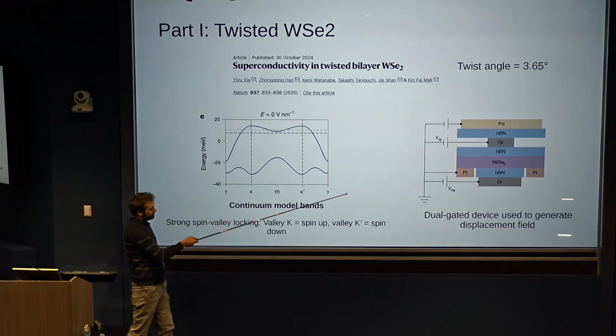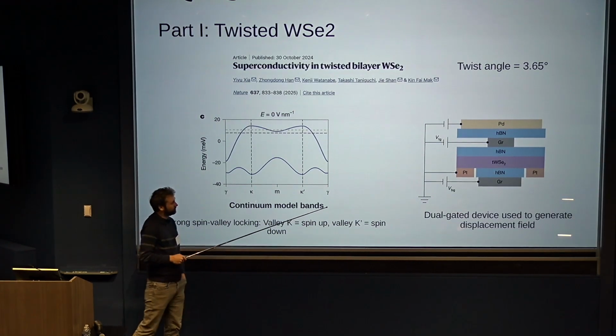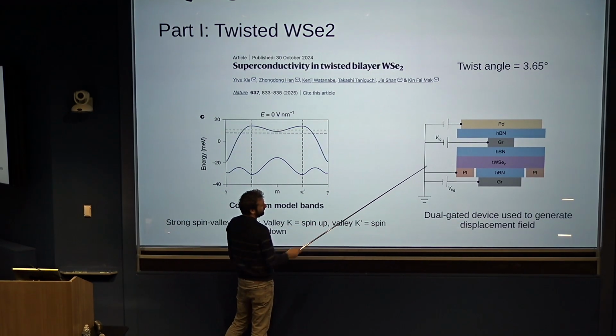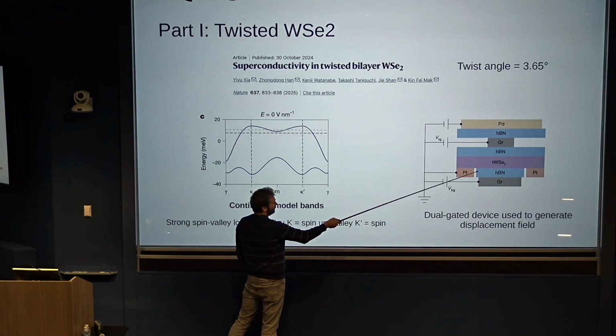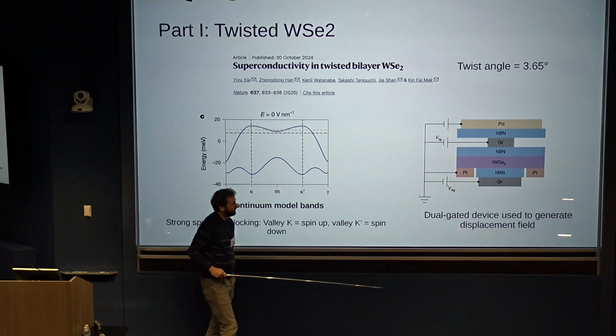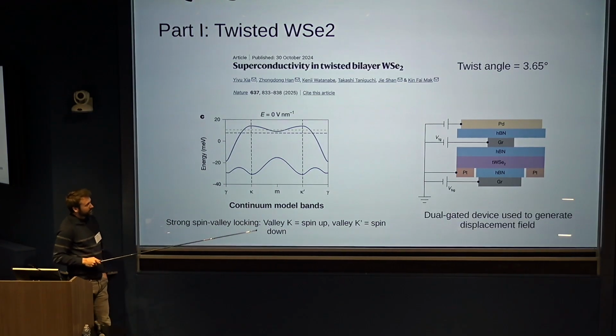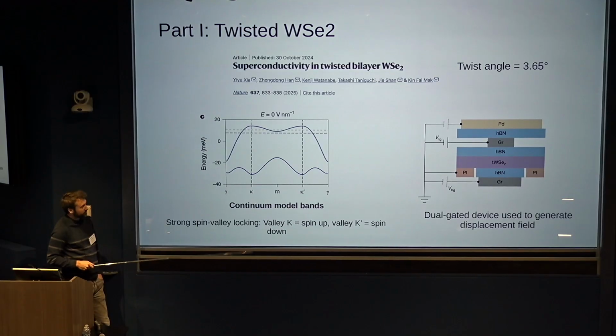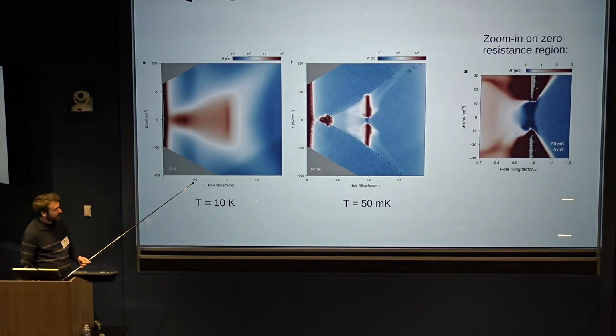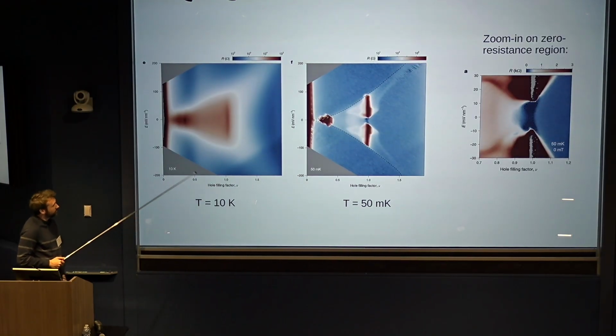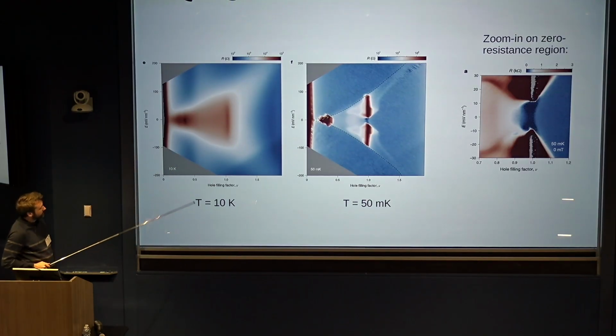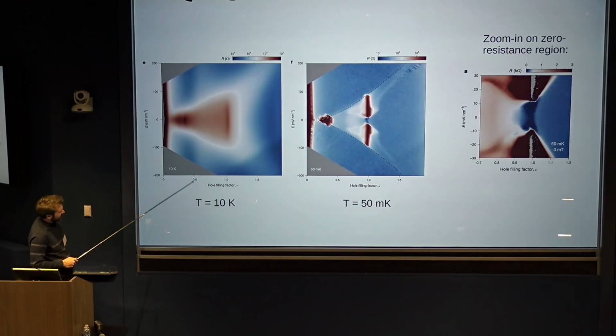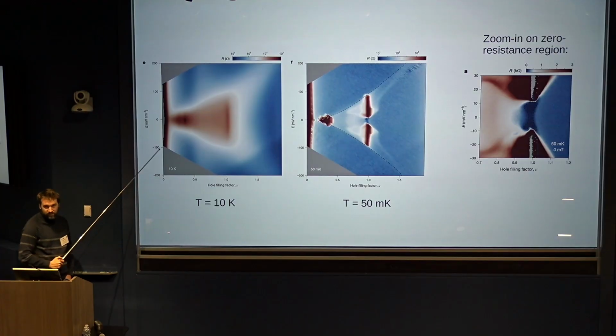On the right here is a cartoon of the experimental device. Here is the twisted tungsten diselenide, then there's some dielectric environment, and then there's a top graphite gate and a bottom graphite gate. With this dual-gated device, the experimentalists can apply a displacement field, an electrical field perpendicular to the tungsten diselenide planes. These are two plots from this experimental paper. They're color plots showing the resistivity at two different temperatures. Along the x-axis, you see the hole filling, and this is the hole filling that I'm most interested in, the hole filling of one hole per Moiré unit cell. And the y-axis here is the displacement field.